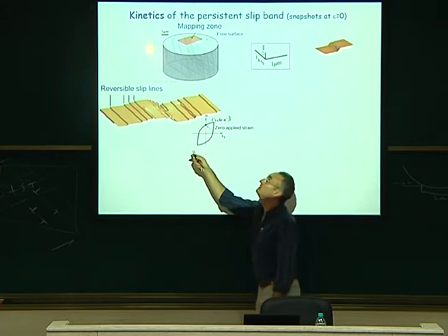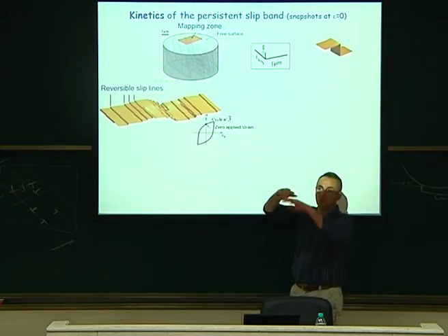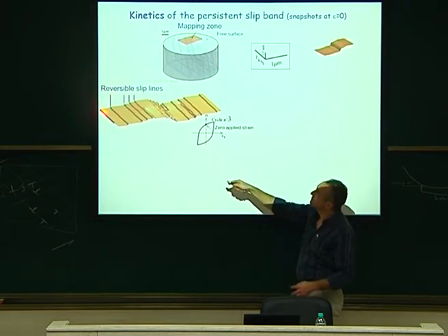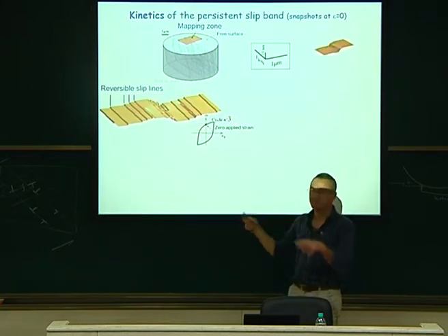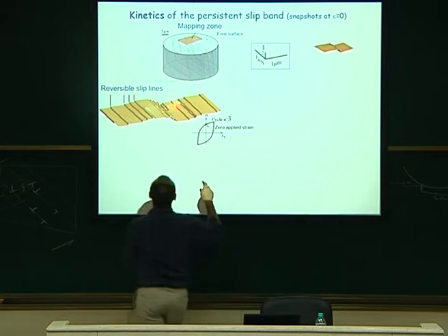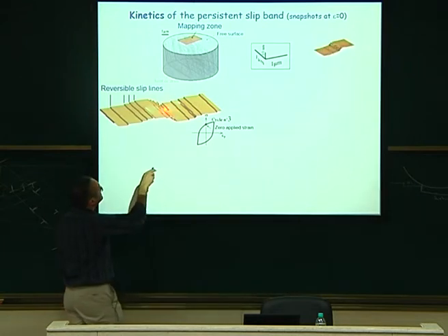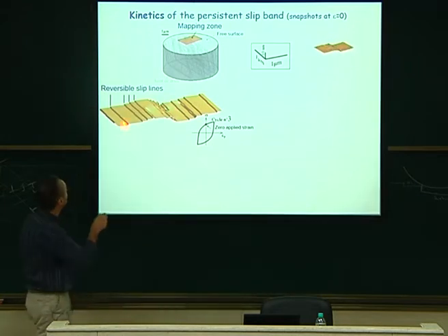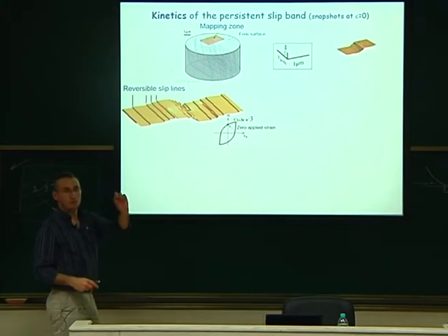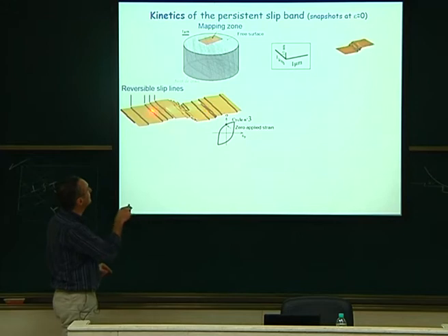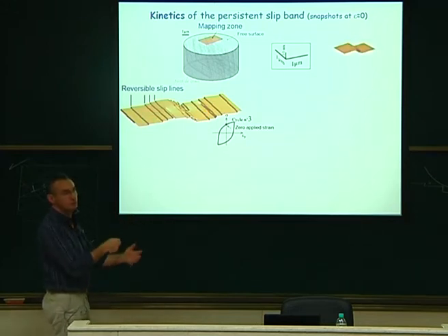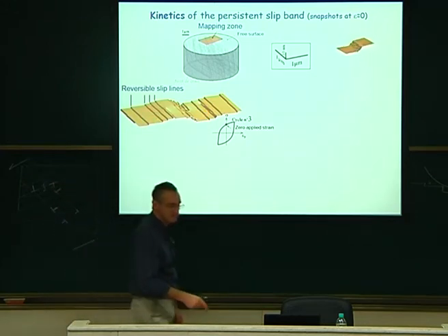So it means that globally the surface is flat. And then you can see it's not exactly flat. You have some positive and negative shape, but globally it is 0. And you have a starting extrusion forming here. You can see the beginning of the extrusion. You have also many steps for which the magnitude is 1 Burgers vector. So those are just one dislocation that escaped at that place. And it will be easy to remove those steps.